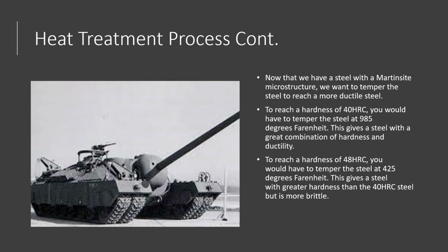And to improve the ductility of this, we must now temper the steel. If you want to reach a hardness of 40 HRC, you would have to temper the steel at 985 degrees Fahrenheit, which gives the steel a great combination of hardness and ductility. And to reach a hardness of 48 HRC, you would have to temper the steel at 425 degrees Fahrenheit.